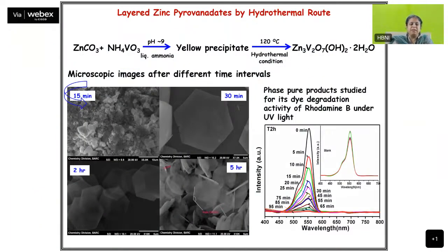But this was one work that we did in our lab. We wanted to synthesize this layered compound. We started with zinc carbonate and ammonium vanadate, and mixed them. I got a yellow precipitate. Then I put it in a Teflon container in an autoclave, heated at only 120, not more than that, for 6 hours. Here I varied the duration also to see whether I'm getting the product or not. The beauty was even 15 minutes of autoclaving was giving me the product.